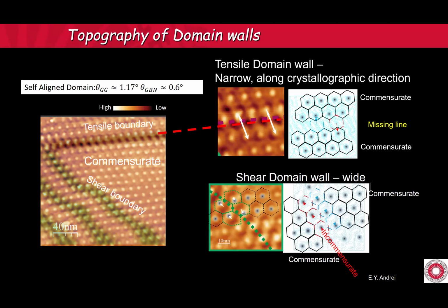In a shear boundary, on the two sides of the boundary, the moires are displaced in opposite directions. The tensile domain walls are just about one Moire lattice wide. The shear ones are much, much broader.